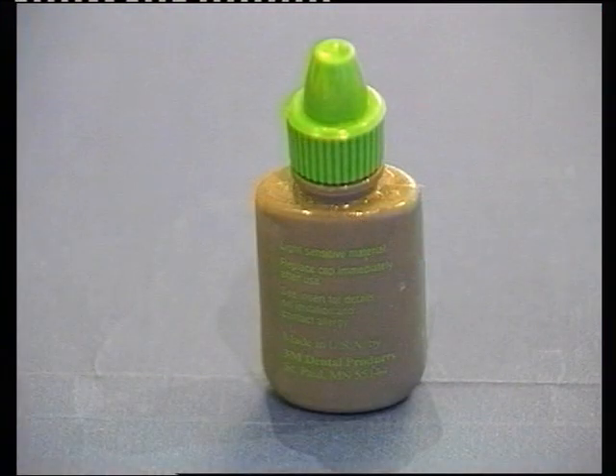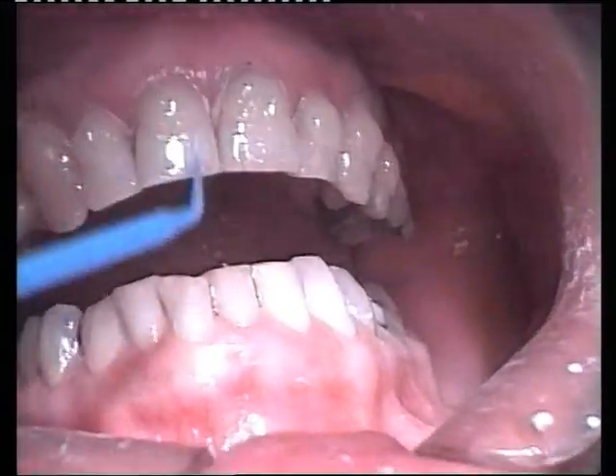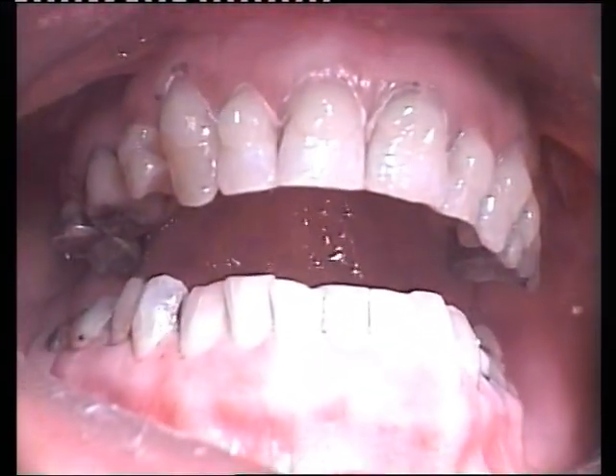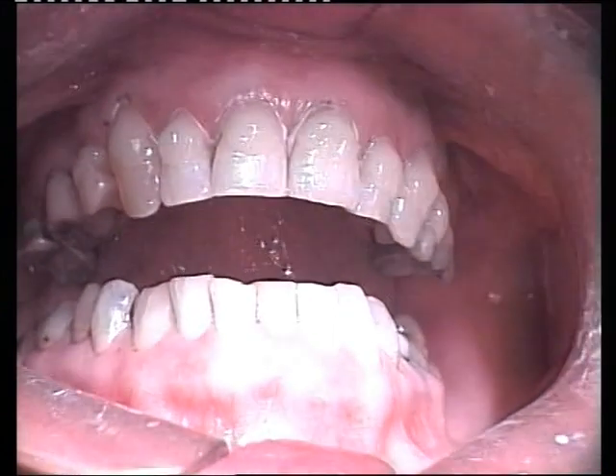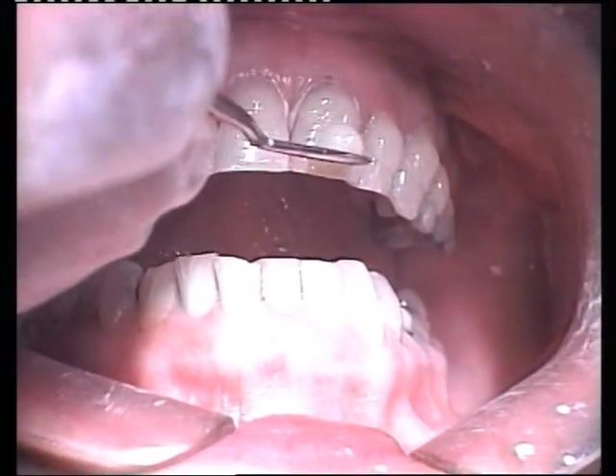If resin-modified glass ionomer bond is used between layers of resin during laminate development, lines of the light-cured glass ionomer will appear across the laminate surface. It is therefore necessary to use a standard bonding resin when layering. The resin bond is brushed over the composite and resin ionomer bond on the tooth surface.